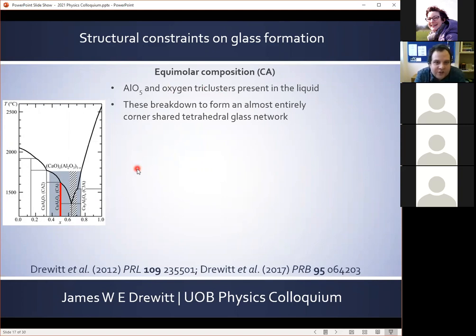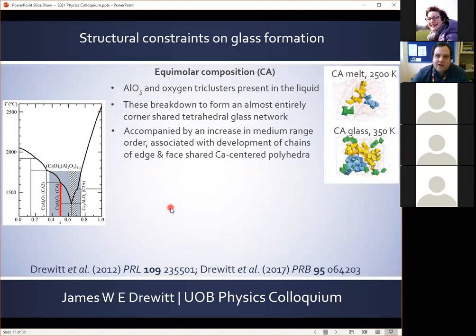However, using levitation and deeply undercooling the melt, these structures break down, and we're able to form an almost entirely corner-shared tetrahedral glass network. And this is accompanied by an increase in medium range order, which is associated with the development of chains of edge and face shared calcium polyhedra shown here. And this is what contributes to the development in medium range ordering, which we observed in our fast synchrotron X-ray diffraction measurements of solidification processes.